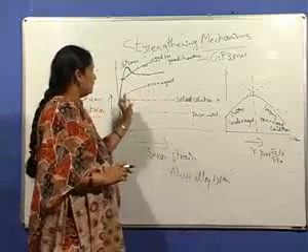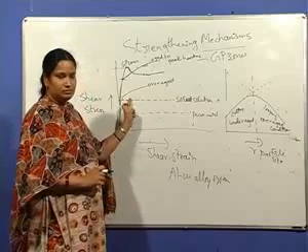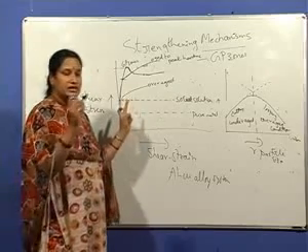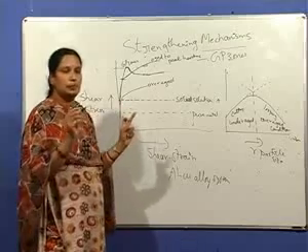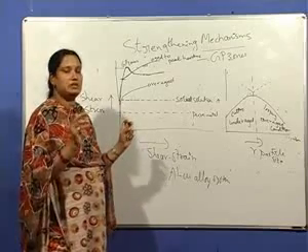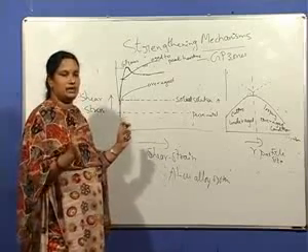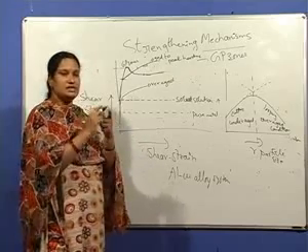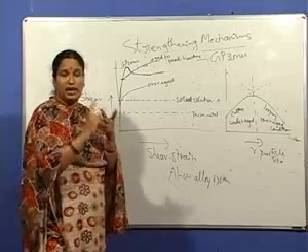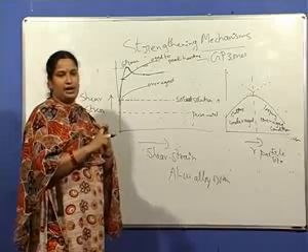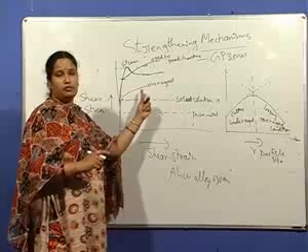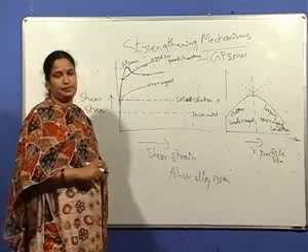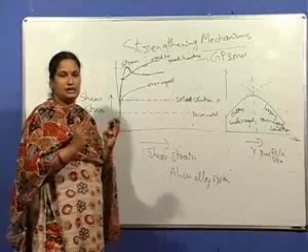In the overaged, the yield strength is lower, but the dislocations form loops around the precipitate particles, the coarser precipitate particles. Because of these loops that are formed, the dislocations form tangles, and the rate of strain hardening is higher because of the formation of these tangles.